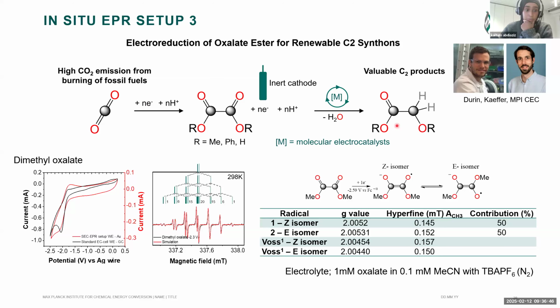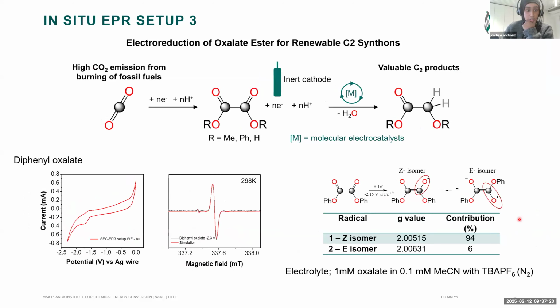And that's what we did, where we applied a potential. So here I applied a 2.3, where the reduction is happening. And then I see an EPR signal with 7 lines, and that follows very nicely a Pascal triangle. So with this, we were able to identify the radical intermediate in this reaction, and we saw that we were having 2 different isomers. So we saw the Z isomer and the E isomer in 50-50% contribution.